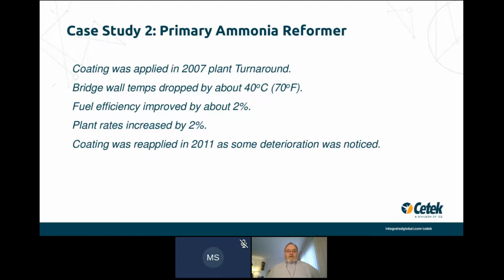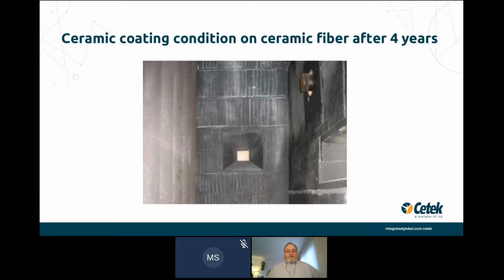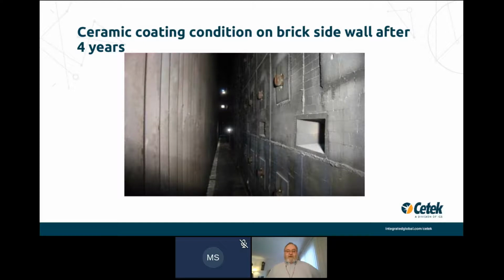We reapplied the coating in 2011 as some deterioration was noticed. And you'll see that in a chart I'll show later on. This is the condition of the coating after the first 4 years. All looks in very good condition. The white lines are where the fiber modules have shrunk during the cool down, which is perfectly normal. This is another shot looking down the sidewall. You can see the flat flame burners in the wall.